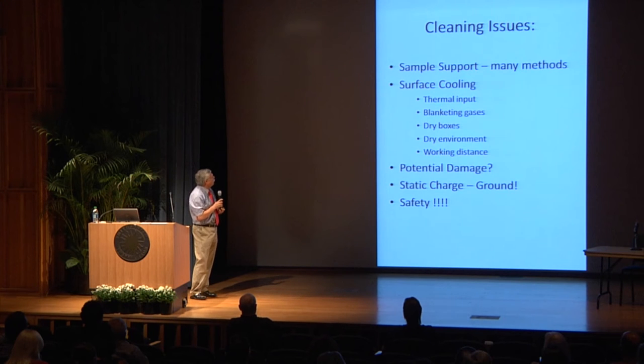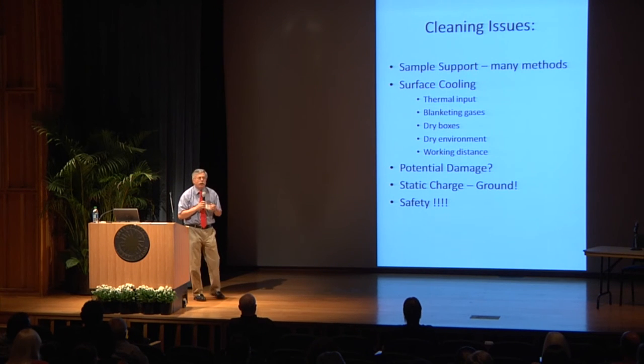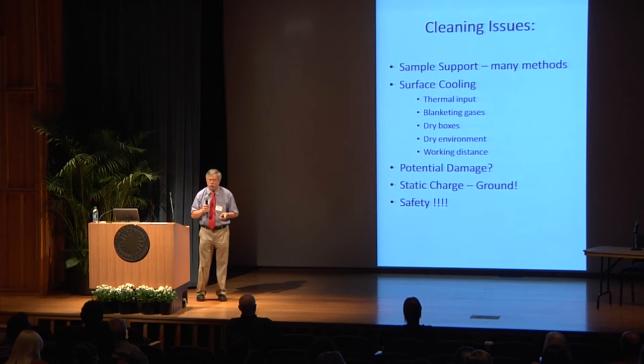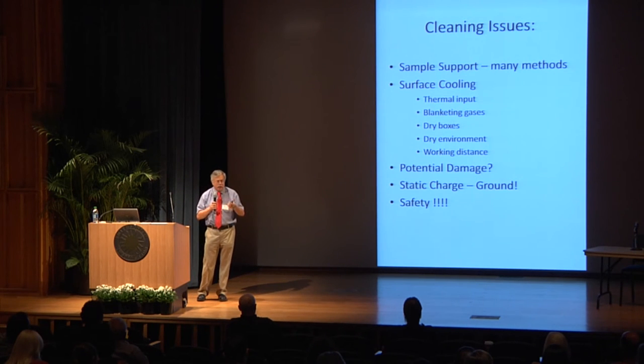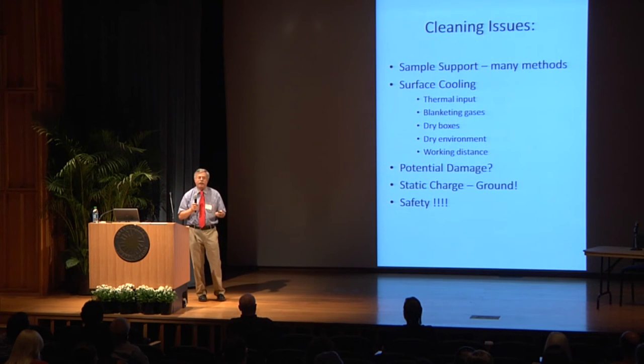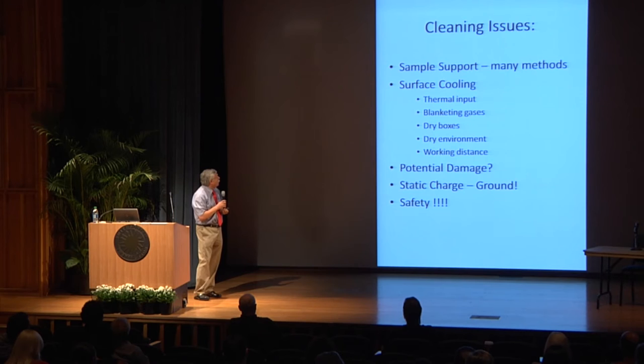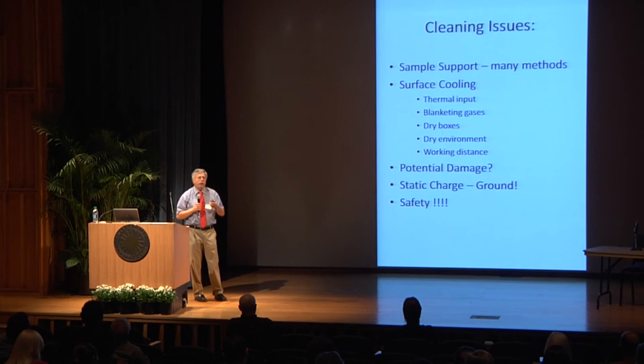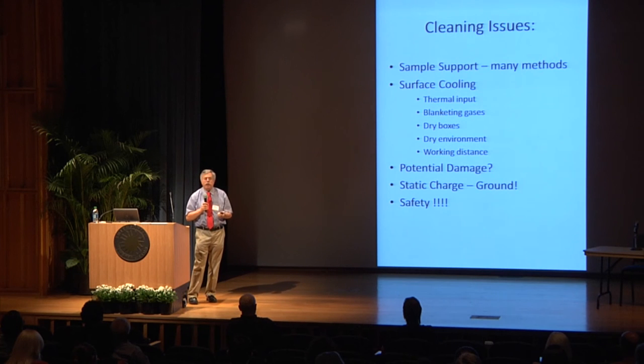The most critical, difficult issue is what's called sample cooling. We're dealing with dry ice. It's cold. So as soon as a cold substance hits a surface, that surface cools. You're going to get moisture condensation if you're in open air, especially on a day like today where it's so humid. So there's ways of getting around this problem. Generally for glass and silicon wafers and metals, you just heat it a little up to like 30 to 40 centigrade. That's enough. You keep the thermal input while cleaning, it works.